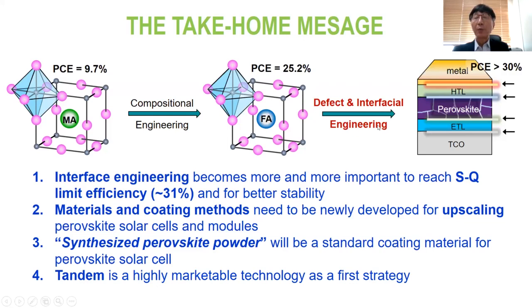engineering is very, very important, and also the bulk engineering at the same time, to remove some defects for recombination. Therefore, interface engineering becomes more and more important to reach the theoretical efficiency of around 31%. And interfacial engineering also guarantees improved stability. And for upscaling, the materials and coating method need to be newly developed.